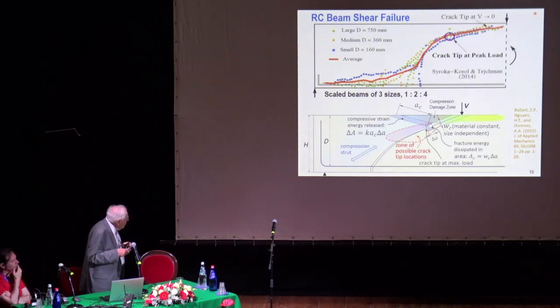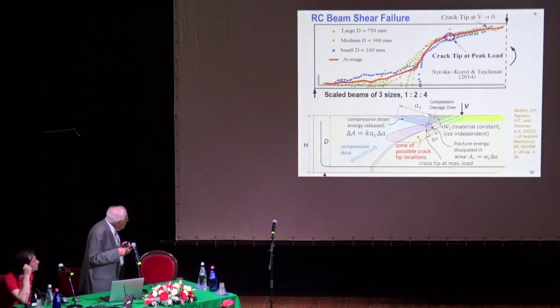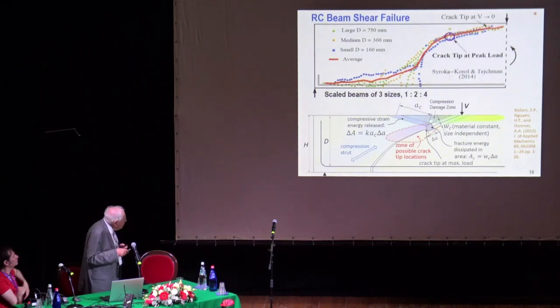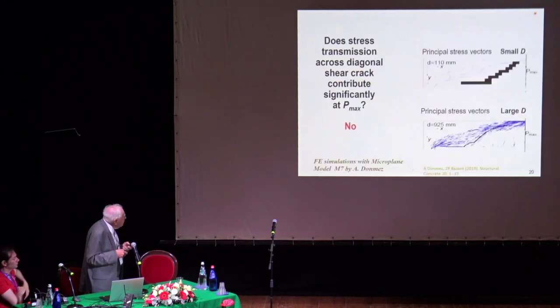And then it propagates. And here the fracture energy is zero because another big compression develops prior to the crack. So this is not failing due to the main crack which we see afterwards, but failure is actually due to the compression strut, what they call the strut and tie model. And failure occurs by propagation of the band of splitting cracks sideways and then exposes this parameter outside. Again, note this compression strut area grows as the square of the structure size, while the length of this band propagation grows linearly. So again, part of the energy is linear, part of it is quadratic, so size effect is obviously automatic.